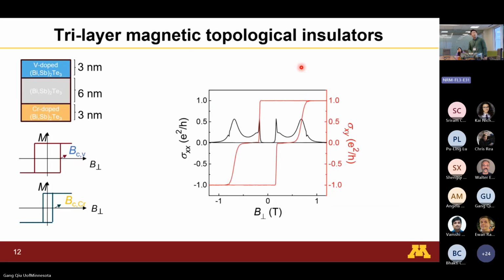All right, so what we did, we took it a little bit further to create this tri-layer magnetic insulator. Okay, so I remember I told you we can add magnetic dopants into topological insulators, right, with MBE. Now, the advantage with MBE is you can add these dopants layer by layer. So what that does is you can actually create different magnetisms on the top and bottom surface. Okay, so it's very easy for MBE. We just turn on and off the shutters, right? So in this case, we use chromium on the bottom layers, and then we use a harder magnetic material, vanadium, on the top layer. So effectively, we can control the coercivity of this top and bottom magnetism.